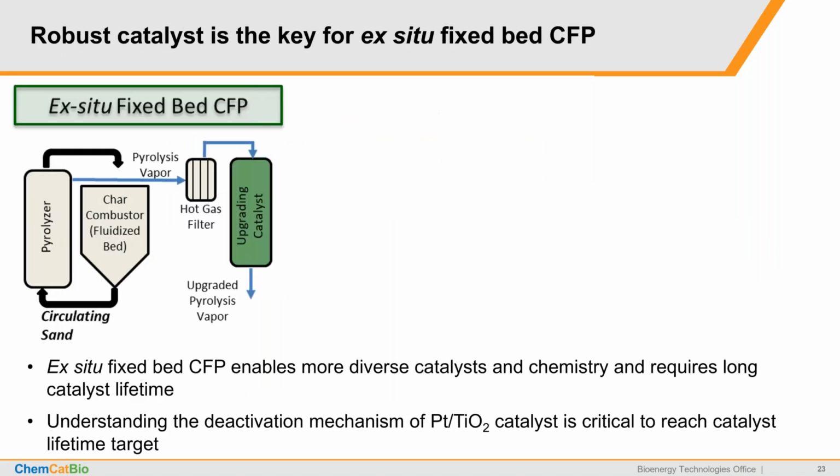So let's now focus on the CFP. CFP, as just mentioned, is a useful catalyst during fast pyrolysis, and here at ChemCatBio, we are more focused on this ex situ fixed bed CFP. Basically, after the fast pyrolysis reactor, the pyrolysis vapor will be cleaned by a hot gas filter, and then the vapor will go through a fixed bed reactor to do various reactions to upgrade this vapor into an improved bio-oil for hydrotreating.